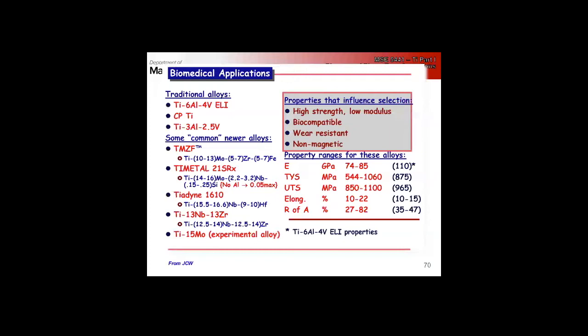Why is modulus important? Low modulus is important for biomedical applications. Bone, right? Ideally your stiffness would be a perfect match for bone, because bone isn't constant. It's constantly remodeling. It's a living tissue, so it adjusts to the stress levels that it sees. And when you have a stress mismatch, you end up with bone remodeling around an implant that is different than it would be if it wasn't there. So ideally, high strength, low modulus, biocompatible.